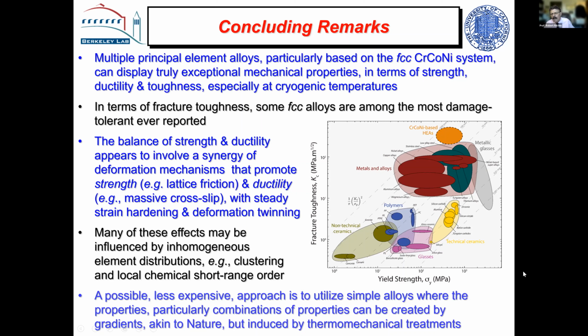This is the Ashby plot. There are the metallic glasses. They're very strong because they're amorphous, but these cobalt, chrome, nickel materials have some of the highest toughness that we've ever seen. To me, it's associated with a generation of a series or a synergistic sequence of deformation mechanisms, which kicks in at increasing strain to prolong strain hardening, which then generates both strength, but inhibits localization to give you very high ductility.